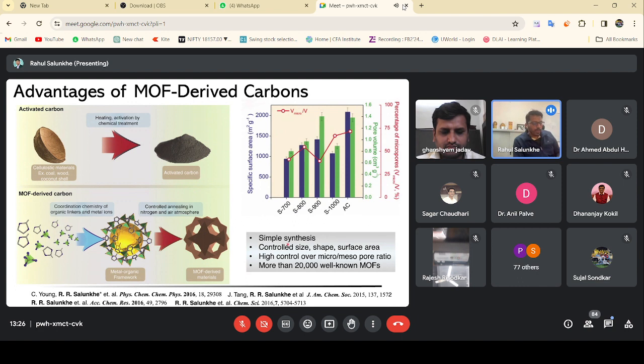What kind of linker you are going to use and what kind of metal ion you are going to use will decide the shape of that metal organic framework, the surface area, the pore size distribution, and the micropore structure. We can decide all of that by use of these precursors. So we can control the micropore to mesopore ratio depending upon the application.